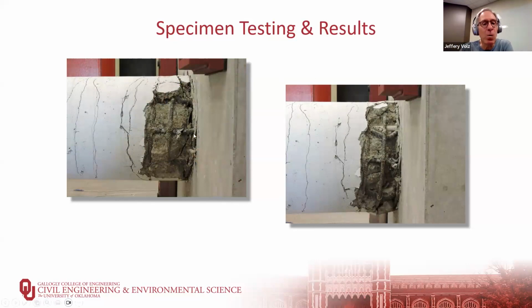You can't see it very well, but here we've actually fractured this bar, which is the bar that's farthest away from the neutral axis. It happened to fracture very near where we had a strain gauge on it, so you can't see it very well. These two bars are still okay. More cycles for the picture on the right. You can see that we've now buckled that top bar and we've buckled that bottom bar.